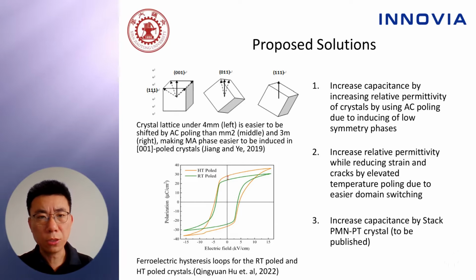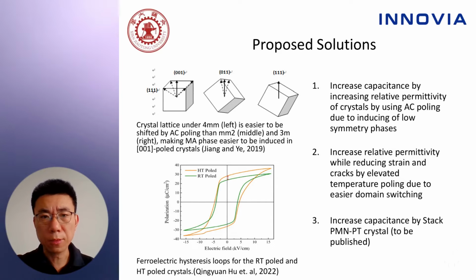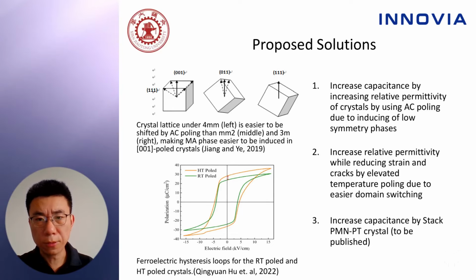The figure on the top left shows that crystal lattice under 4mm symmetry is easier to be shifted by AC poling than mm2 and then 3m symmetries, and these correspond to 001, 011, and 111 oriented crystals. In short, AC poling is easier to be introduced in 001 poled crystals, making monoclinic phase much easier to be induced in those crystals.